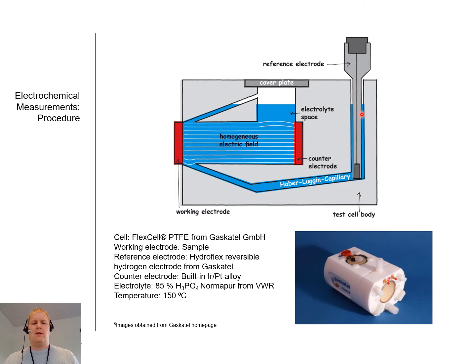You have a reference electrode that was a HydroFlex reversible hydrogen electrode, and a counter electrode which was a built-in iridium platinum alloy. The measured current was between the working electrode and the counter electrode, and the measured potential was between the working electrode and the reference electrode, creating a much more accurate potential value. The electrolyte used in this experiment was concentrated phosphoric acid purchased from VWR, and we heated up the cell to